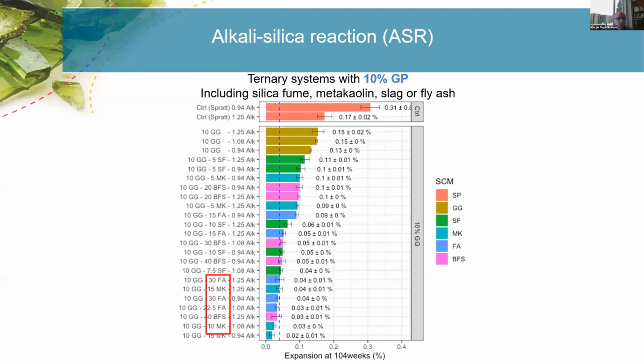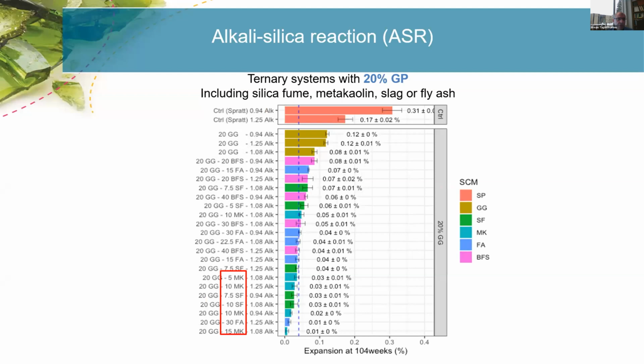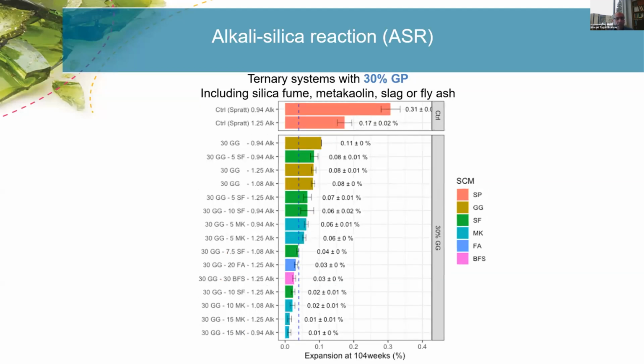And here we did a lot of concretes with Isabelle, and the work is ongoing with another student. And we found that some of the ternary blends are working very well with metakaolin or another pozzolan or fly ash, 10%, 20%. Also with 20%, same thing. We have some brackets here where we can see that we are under the limit of expansion. And also 30%, we have also some of them. So actually, we are working with a new student to go to different types of aggregates.